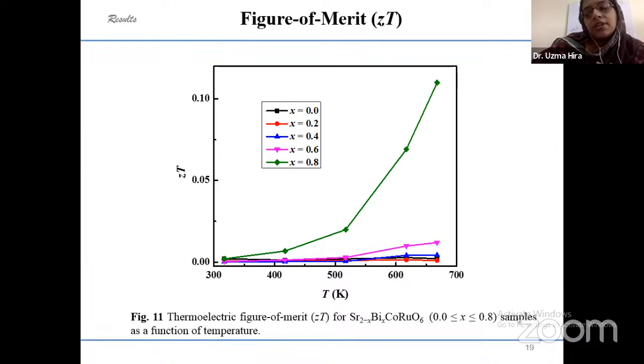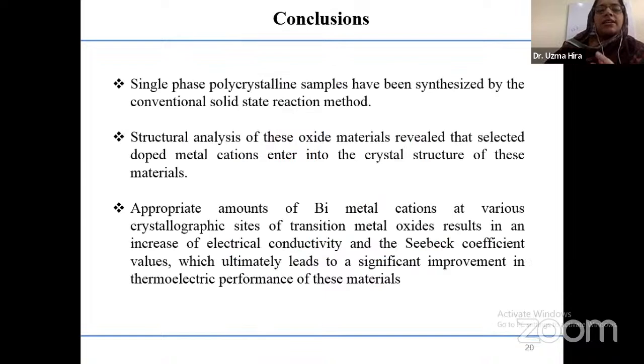We are also working currently, and have a plan to work in future on this material for improving its ZT value further. So we can conclude our lecture that we were successful in preparing the single phase material by using the solid state synthesis method, and we have completely done the crystal structure analysis for these double perovskite materials. We concluded that our dopant, which is bismuth in this case, is going inside the crystal structure and changing it, using the XRD pattern, the lattice parameters and the other parameters we have extracted from this data.